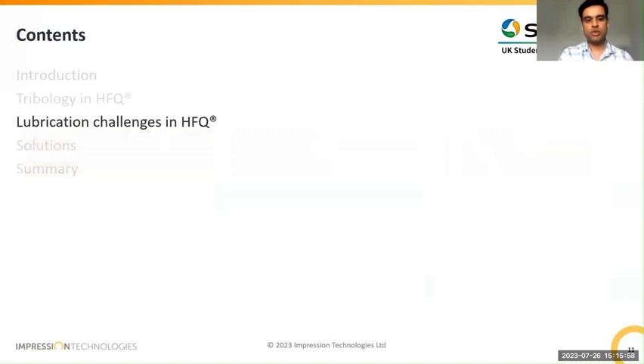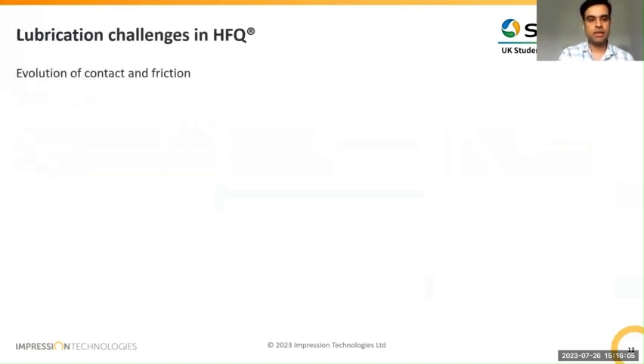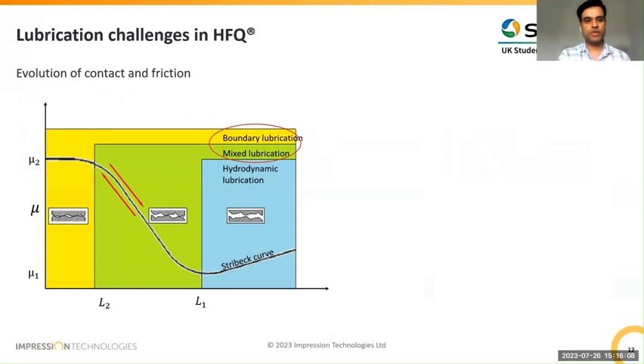So I'm just now trying to make you more aware of what challenges such a contact can bring in. So the first challenge is the evolution of contact and friction. If you look at a Stribeck curve, which we all know, it divides into 3 lubrication regimes. In sheet metal forming, we have these parameters called L1 and L2, which is an extension of the current Stribeck curve, but we account for surface finish in it. So we typically only operate in boundary and mixed lubrication regime. We rarely go to hydrodynamic lubrication or EHD in that regime.